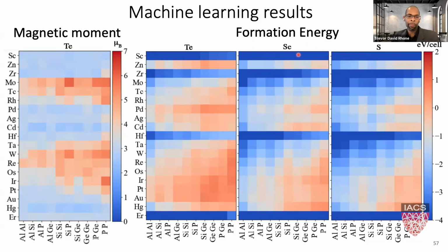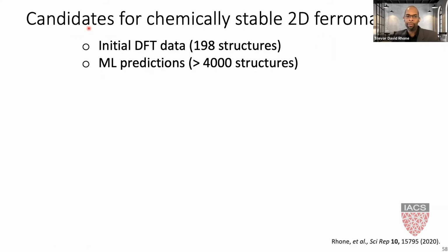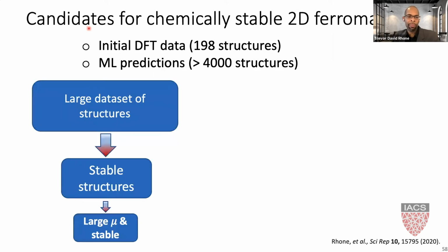So I'm showing some subset of the machine learning predictions for the magnetic moment here, and for the formation energy here, with the usual scheme of A side substitutions on the vertical axis, B side substitutions on the horizontal axis. So these are my machine learning predictions. There were really too many. There are over 4,000 in this particular case. So what I did was I did some screening approach.